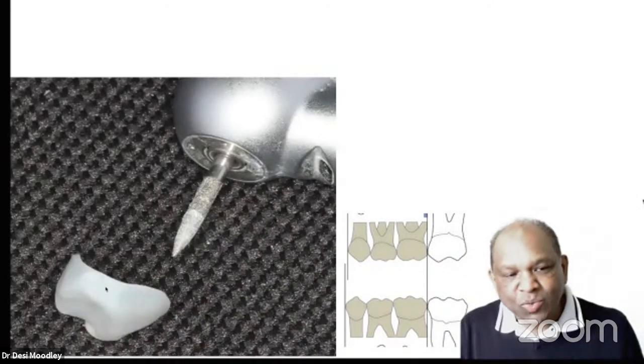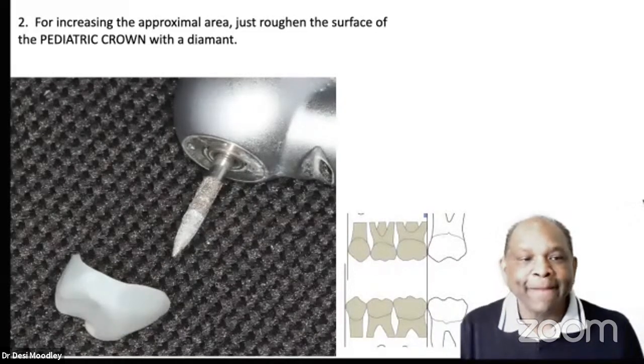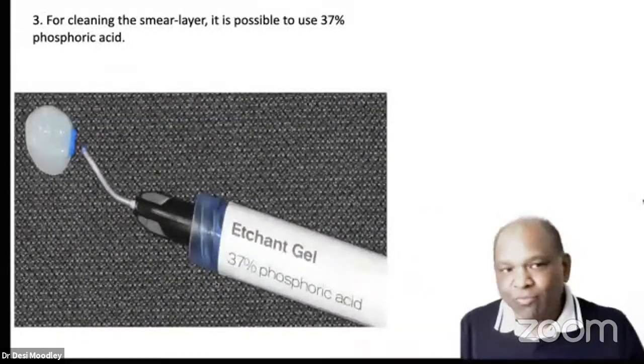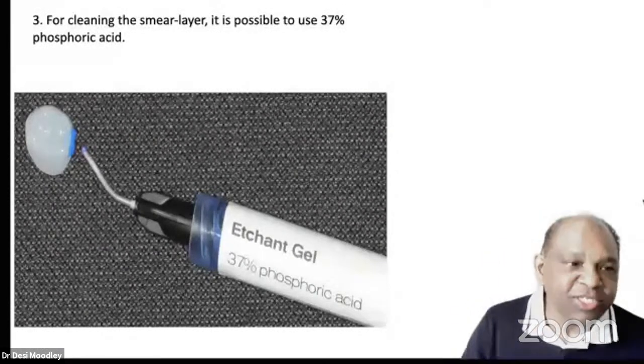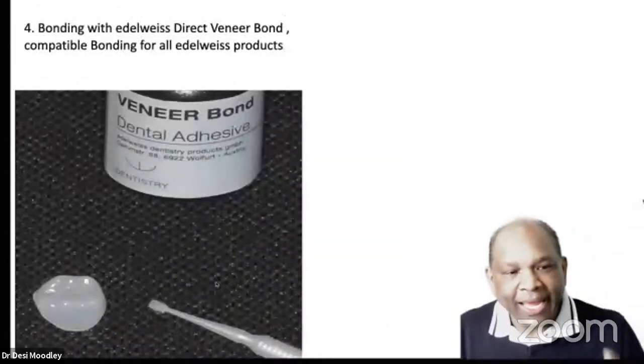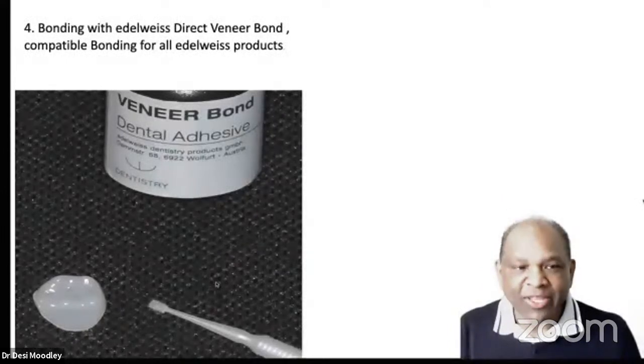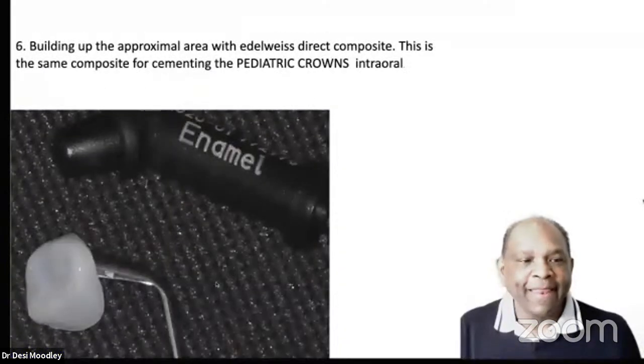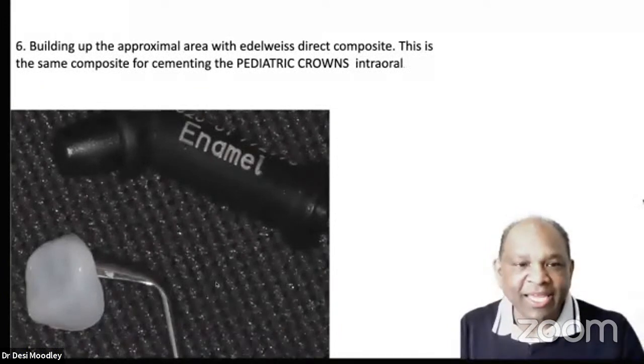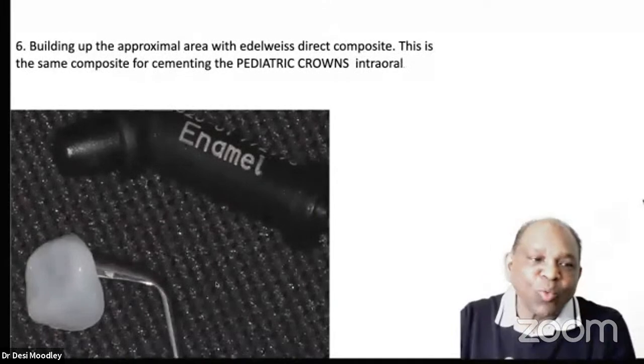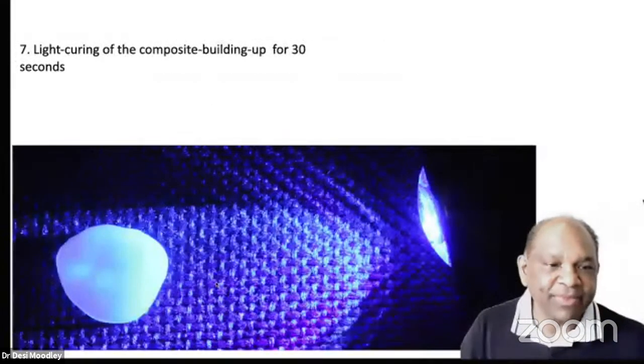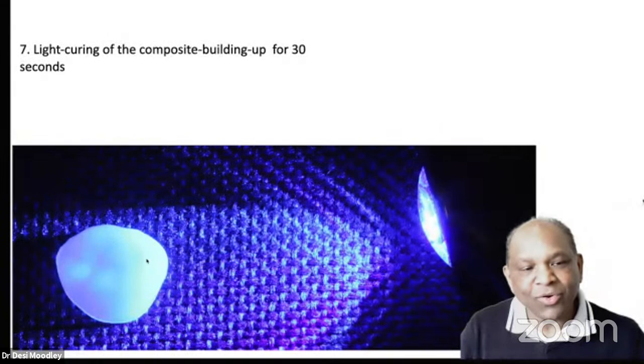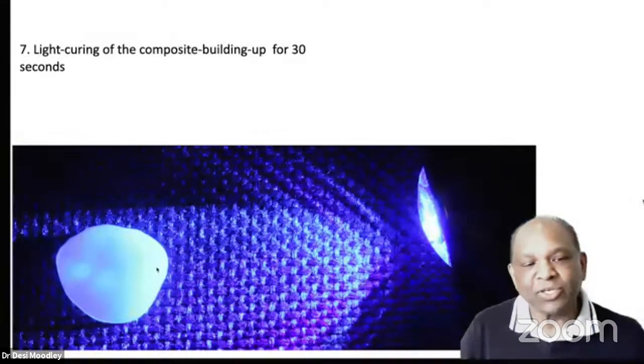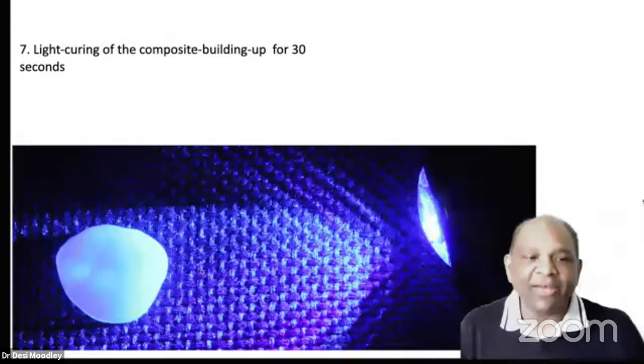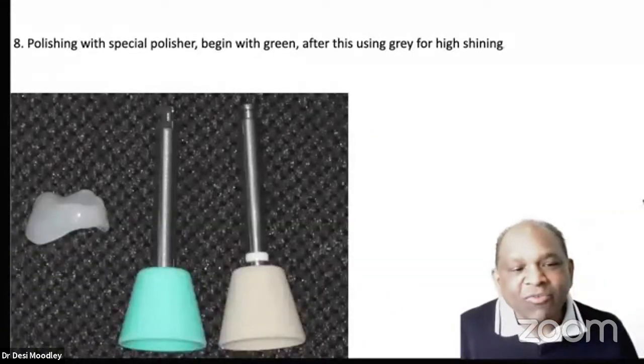So all you need to do is roughen the crown, and then you, of course, can etch it or just rinse it off. Apply some of the Edelweiss bond over that, light cure that, and then place some of the Edelweiss enamel composite to the length that you want to close that gap. So then you light cure that, and now you'll notice that you've got a little bulkier mesiodistal crown. And of course, now this will close that gap mesiodistally. So a very big advantage.